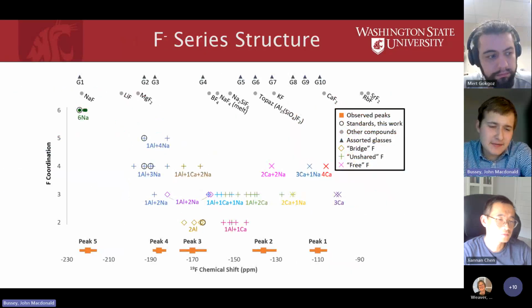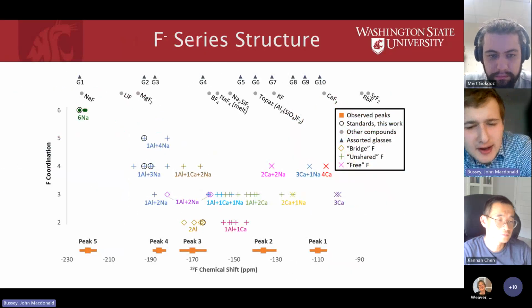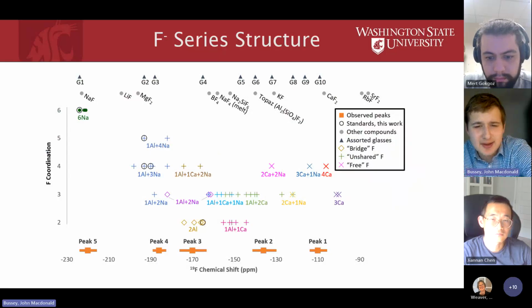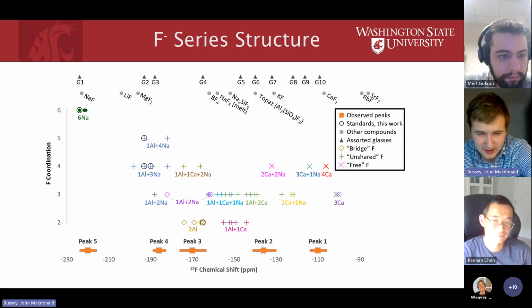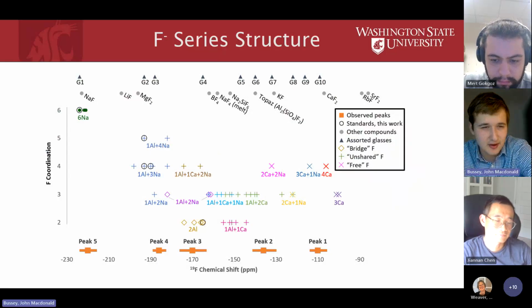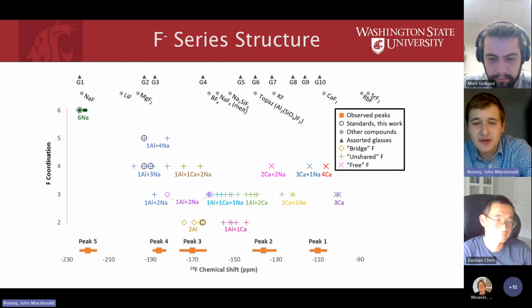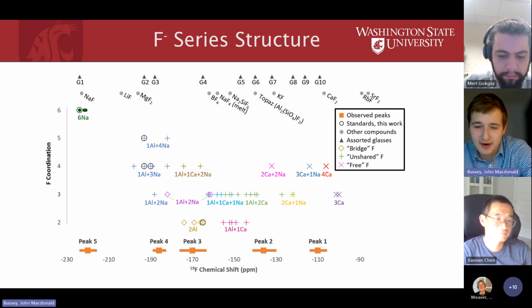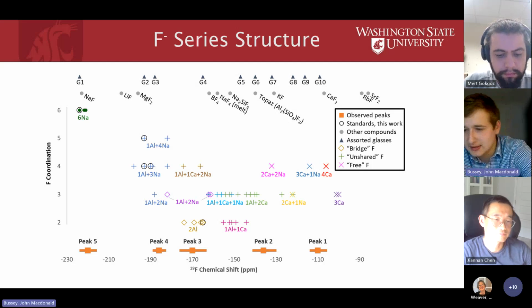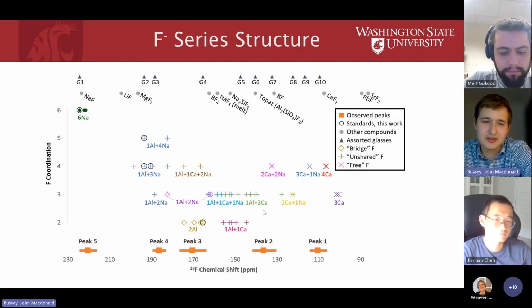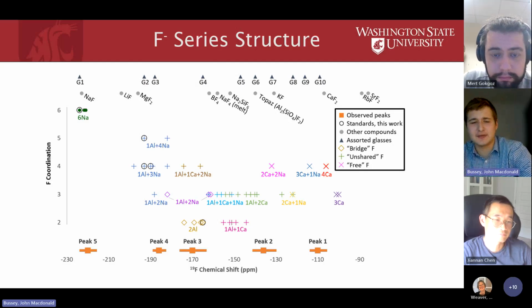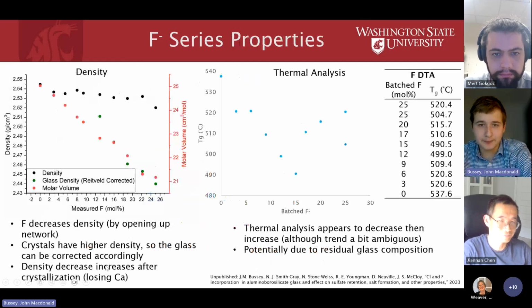And here are our fits from the fluorine NMR, and I mostly put this up here because it took a very long time, and I'm slightly happy about making it. This involved looking through all the literature of all of the fluorine environments ever assigned, and then trying to connect them. But basically, we can show which of the aluminum, calcium, and sodium environments the fluorine goes into, and it's fairly strange that the fluorine is in all of these different environments at the atomic scale.